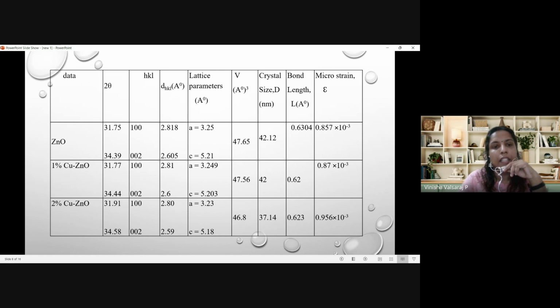Here you can see that as the copper percentage increases, the crystalline size decreases, and also the 2 theta value is shifted in the case of the higher percentage of copper. But in our study, we are mainly concentrated on a minimum amount of copper doped into the ZnO. So for this study, we selected 1% copper-doped ZnO.